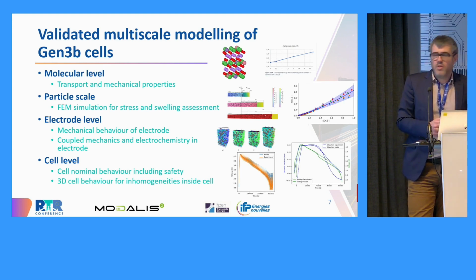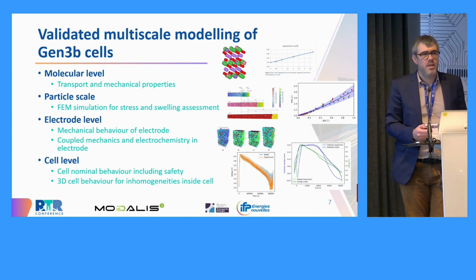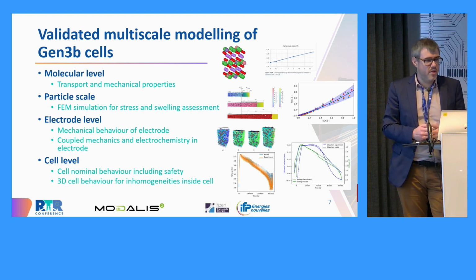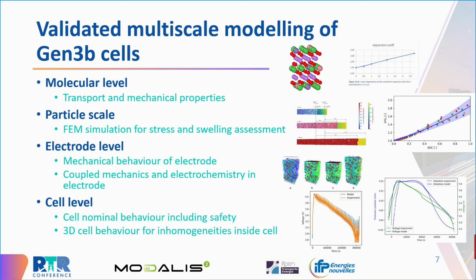But the thing that we were very lucky at is that when we compared the experimental results at the end of the project with the modeling results from the beginning of the project, they were matching quite well. So we didn't have to have a lot of iterations in order to make this validated and calibrated.